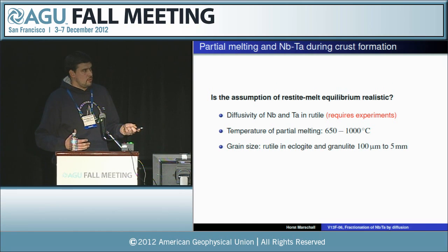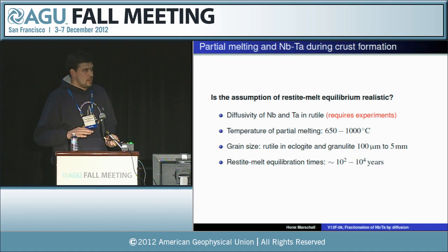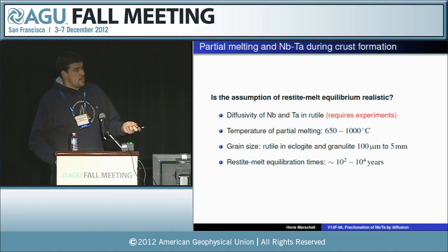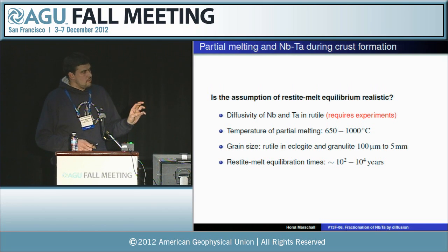Grain sizes of rutile are important. If you look at diffusion, they are typically in the range of 100 micrometers to maybe a millimeter, or even larger in some cases, in the relevant rocks. And restite-melt equilibration times. These equilibration times depict the time that the melt, a partial melt, would stay in contact with the restitic minerals. It's not the time of partial melting overall. That may take millions of years in a high-grade terrain. But the amount of time that the melt has to equilibrate with restitic minerals before it's extracted into pods and veins and is extracted from the whole rock volume. There's some good work that I'm happy to point out to people.